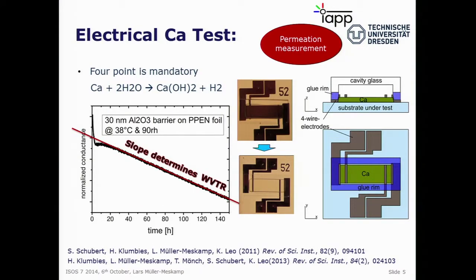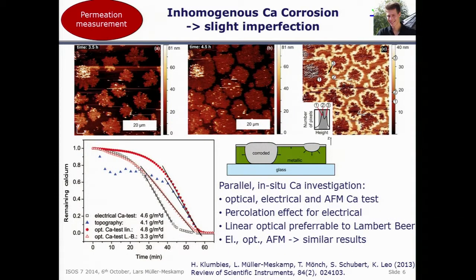Okay, so we stick to the electrical one. If we do that, it looks like this. This is our layout. So here you can see the calcium in the middle. After a while it vanishes, and then it's done. And you measure the conductivity or the current over time, and it gives you a nice linear slope which is decreasing, and that slope is proportional to the WVTR, the water vapor transmission rate. Whenever you measure permeation or talk about barriers, you should always note that there's a temperature and a humidity attached to it.